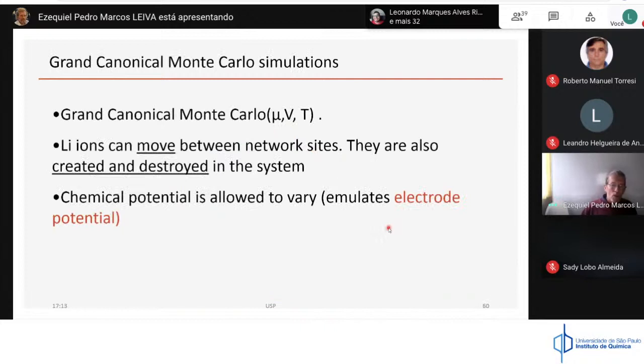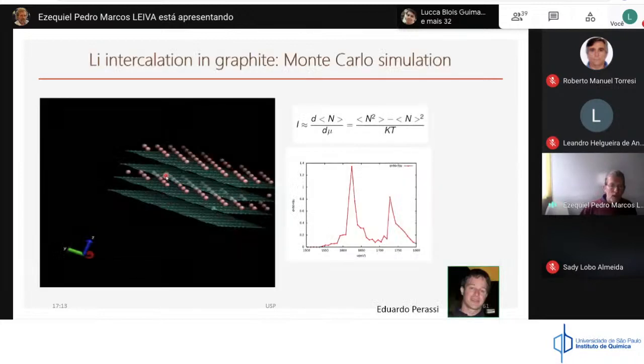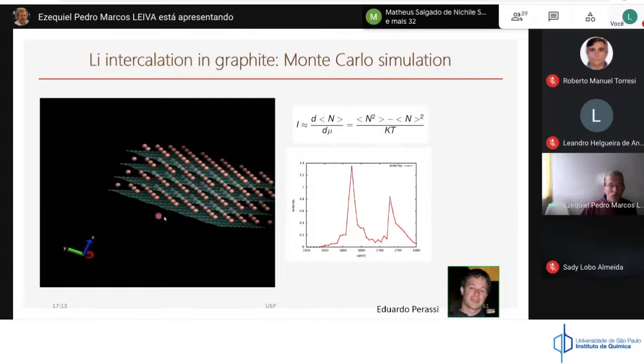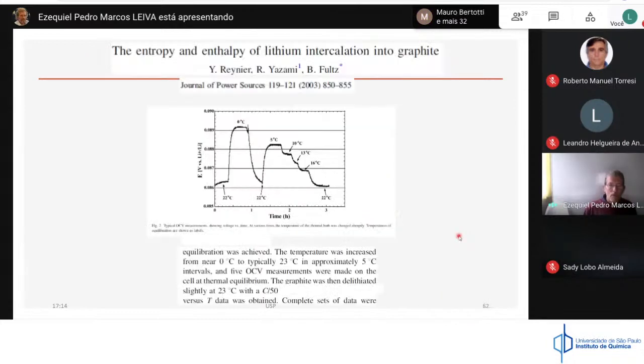Well, you have to make some moves. The moves involve the creation and destruction of particles in the system, and this is a Monte Carlo simulation where you can see first the formation of stage 2 and later the formation of stage 1. From this information, you can see how lithium becomes inserted in graphite. You can calculate voltammograms, for instance, an equilibrium voltammogram. But more important is that you can get from this simulation the entropy of the system. The entropy of the system can be measured, and this has been measured in the literature.